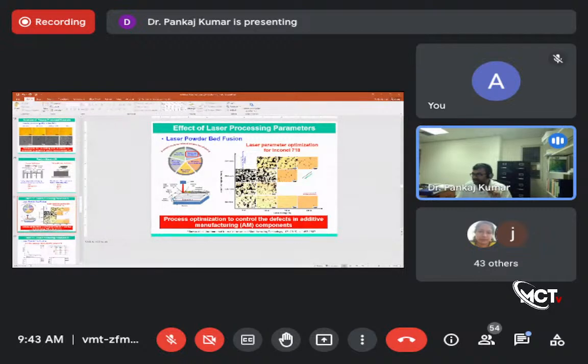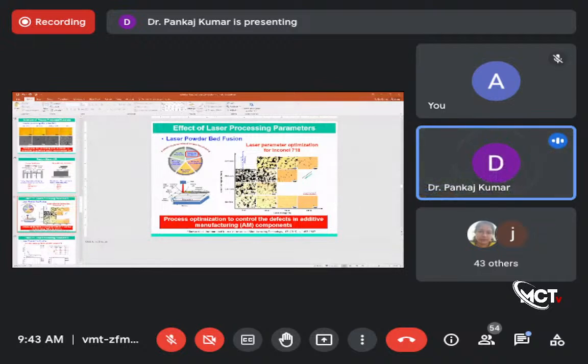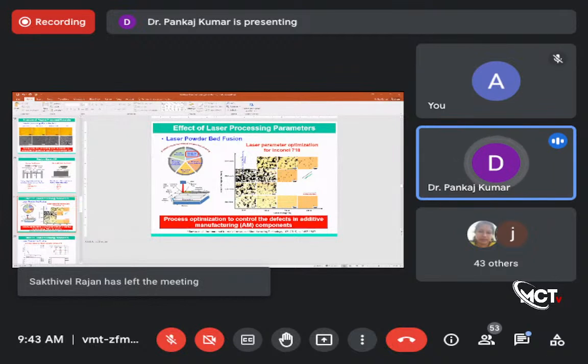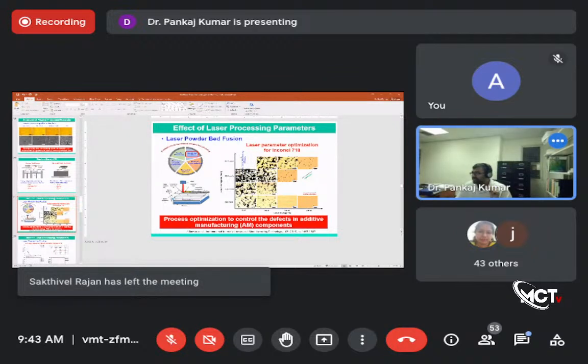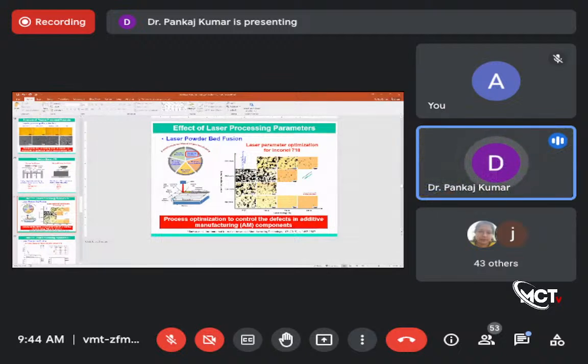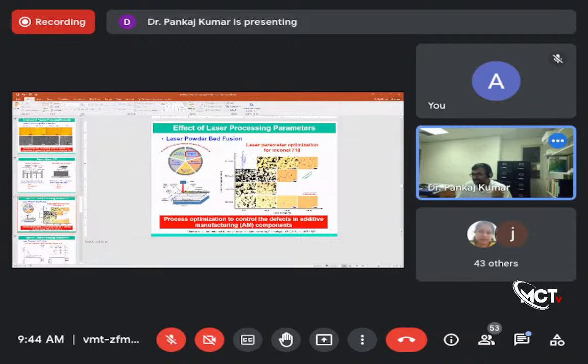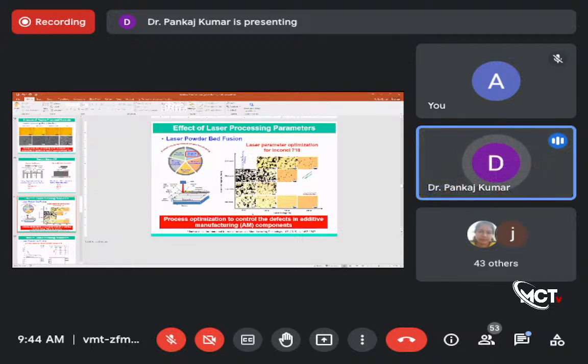So all these are parameters that you can control, right? And if you control that, you can control the laser power density. So that becomes very important, right? This is an example of how the process parameters for the laser change the quality of your product. If you change the speed, you make very bad samples. If you increase the power, you make very good samples, but you increase the cost. So you really want to optimize the condition where you minimize the cost, but you still get the best materials, right? So this is the way to go.